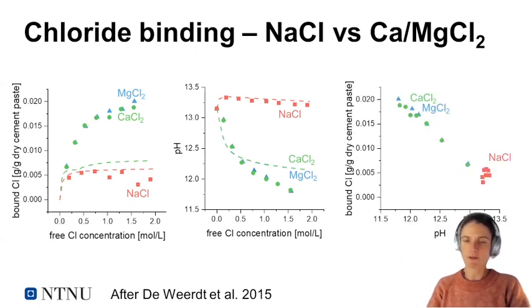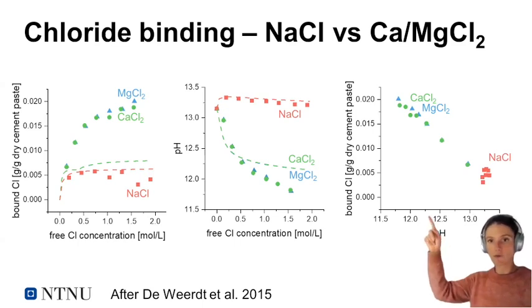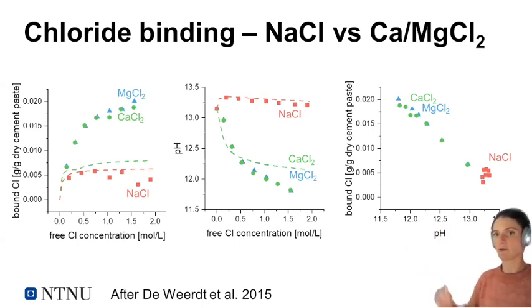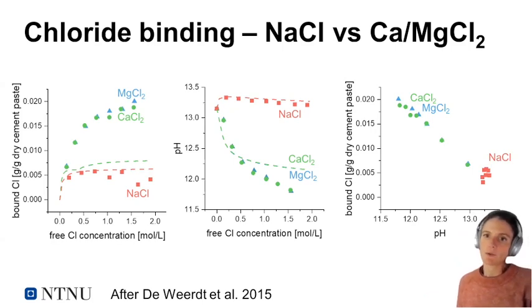And when we plotted the pH as a function of the amount of bound chlorides, we could actually see quite a clear correlation between the two. So the lower the pH, the higher the amount of chlorides that could be bound.